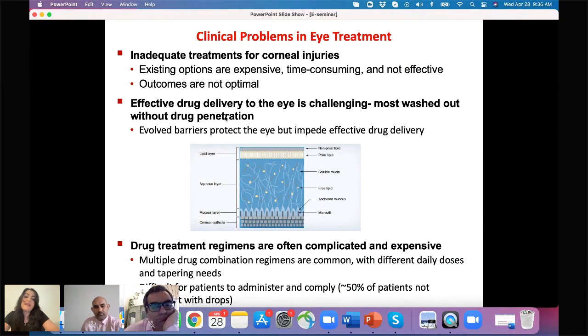The second problem is effective drug delivery to the eye. It's very challenging, and most of the time drugs are washed out without penetrating inside the eye. If you look at this diagram, you see that on the surface of our eye, we have different layers. We have the corneal epithelium, then a mucus layer, an aqueous layer, and a lipid layer on the top. The presence of these layers forms a barrier that protects our eye, but at the same time, it will not let the drug penetrate inside the eye. So this has been one of the limitations in effective drug delivery to the eye.